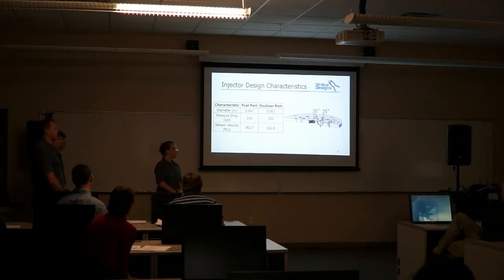streams. As you can see on the screen, we have significantly different velocities entering our chamber, and the densities of the propellant are also significantly different. It is most optimal to have the propellant stream after impingement be axial along the combustion chamber. Therefore, we have gone with a 35-degree impingement for the fuel and a 25-degree impingement for the oxidizer. This results in less than 1 degree of difference between the propellant stream after impingement and the vertical axis.